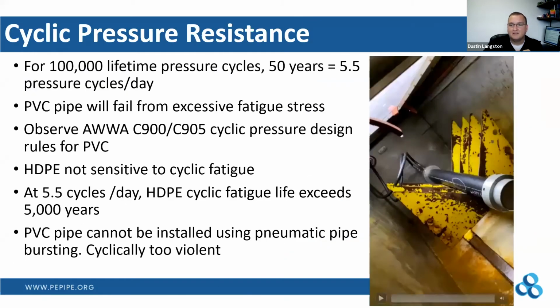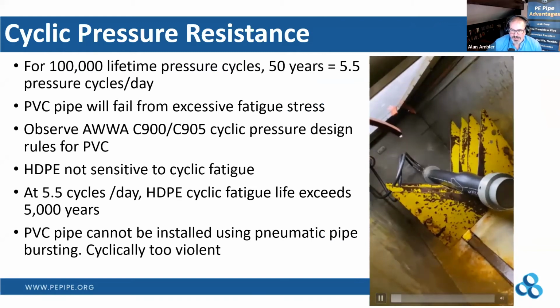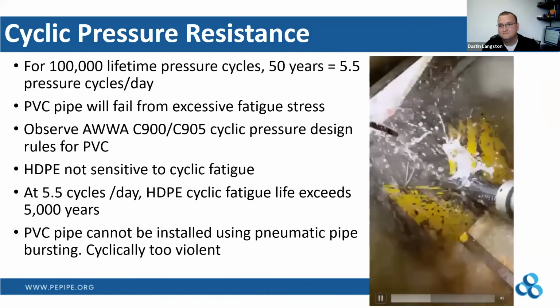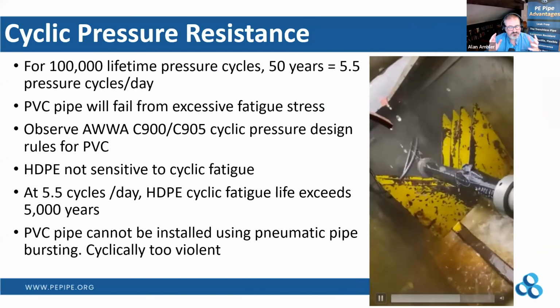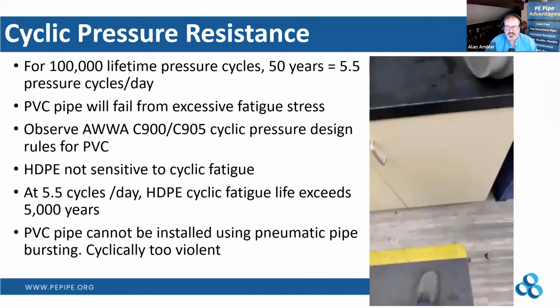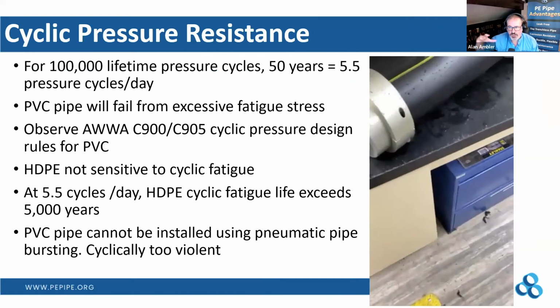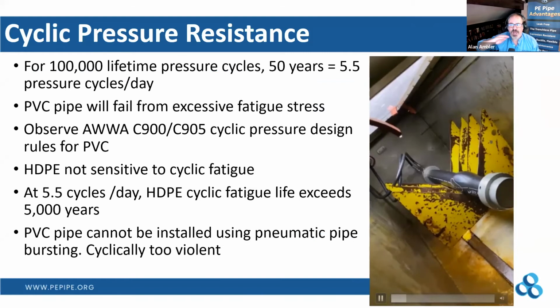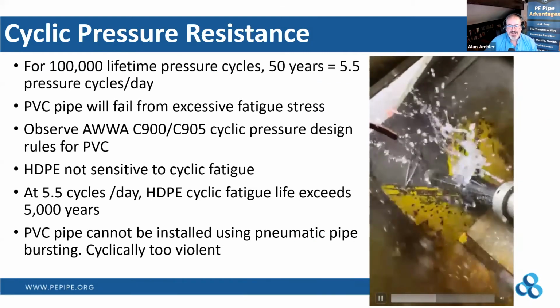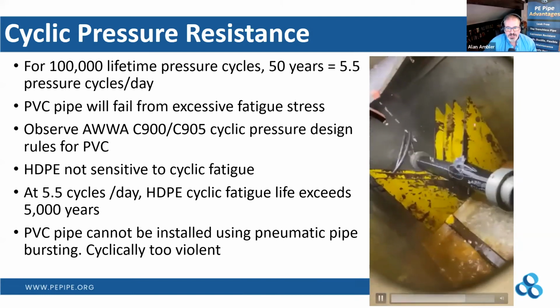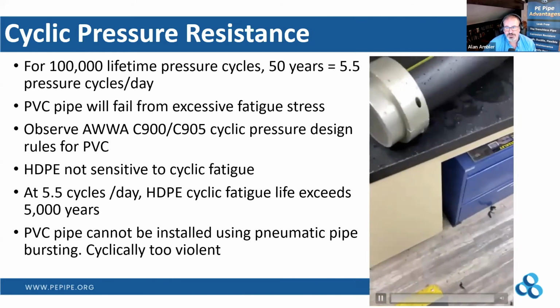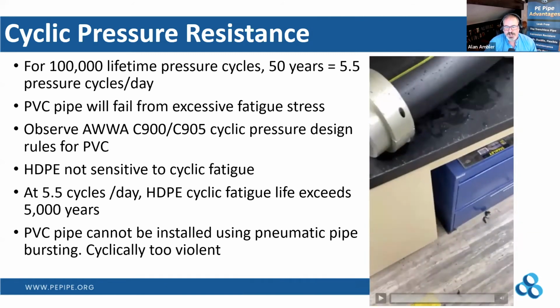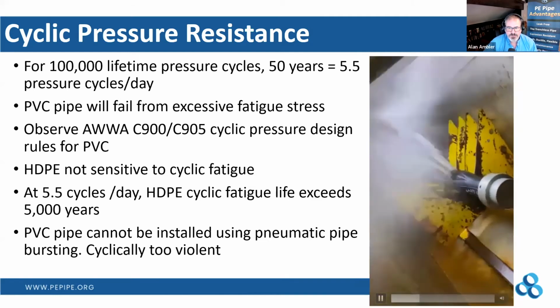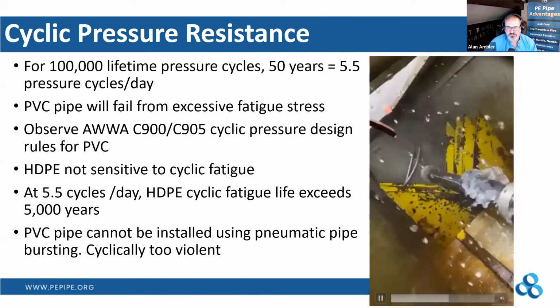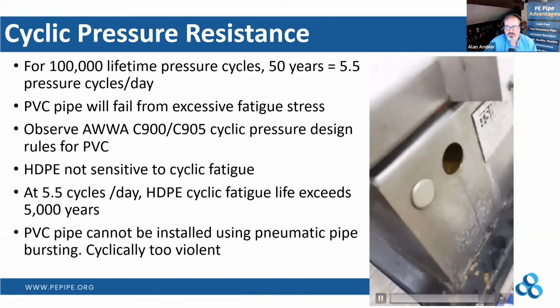So we put that video in for you, Dusty. While it's not the constant pressure surge that they test at the facility for the resin, where they have lots and lots of these pipe samples in different controlled temperature areas, constantly running that occasional and recurring surge through it to prove the hydrostatic design basis that makes up the pressure rating of this pipe, this test is a quick burst test to show you, at the extrusion facility, what it could be like as it fails. This pipe, if it's a DR11, from what I've seen, could be failing at 1600 plus PSI through that quick burst test.